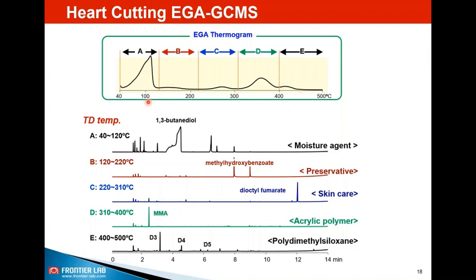In this slide, basically what we are showing is, if you have an EGA of this nature with 5 different zones, you can generate 5 different chromatograms. By doing that, you are getting very clean chromatograms. So you can get all the minute information that may be missed if you are doing a flash pyrolysis for this kind of sample. This sample is actually coming from cosmetics, an eyeliner, where the eyeliner performance is decided by the moisturizing agent, preservative, the skincare chemicals and the polymer base. So here they always prefer to do this kind of heart cut to look at minute information, which may not be possible with flash pyrolysis. So this is a situation where people are looking for heart cutting.